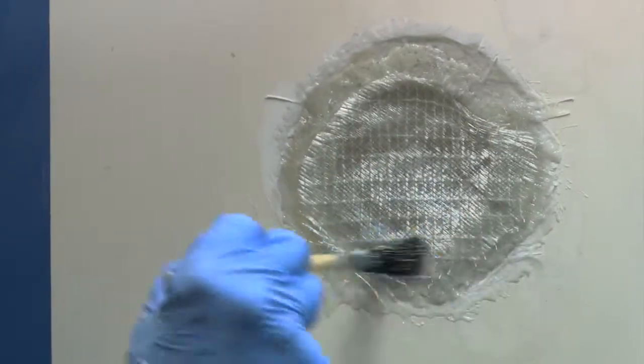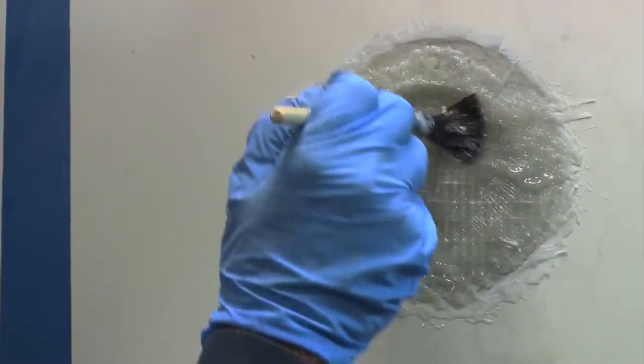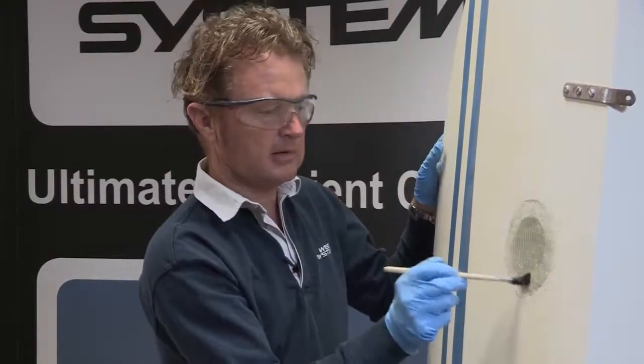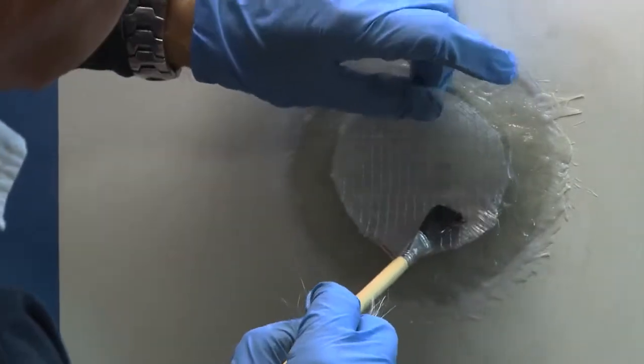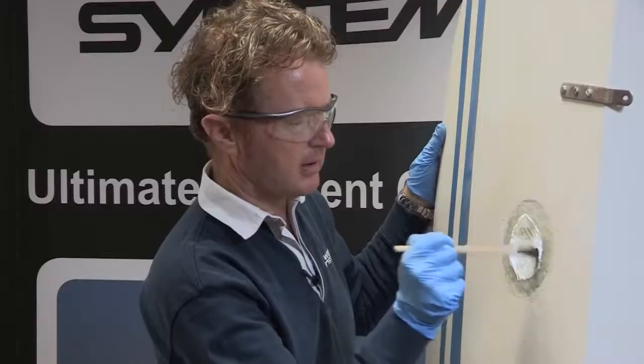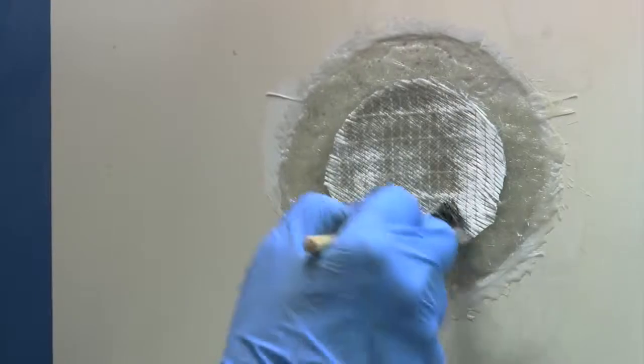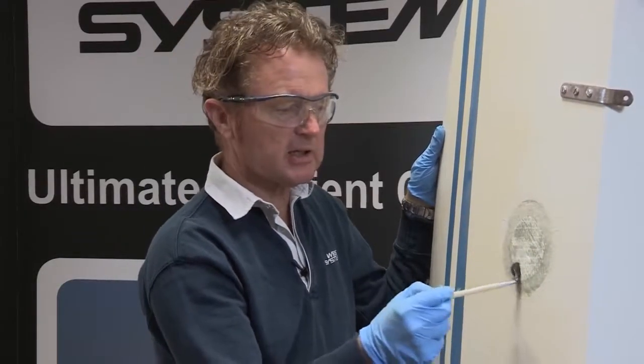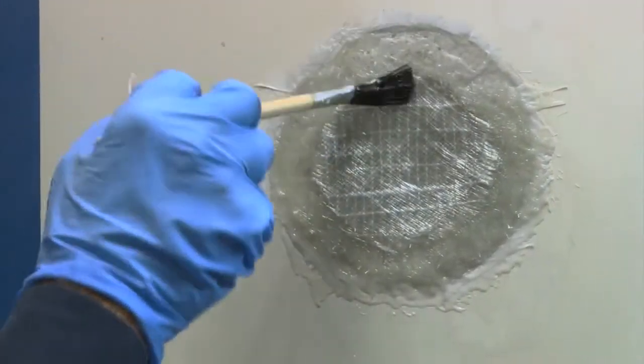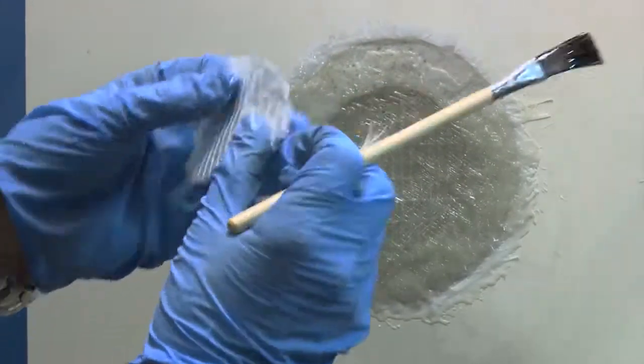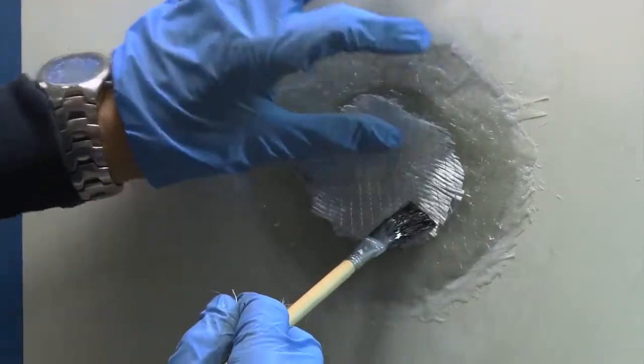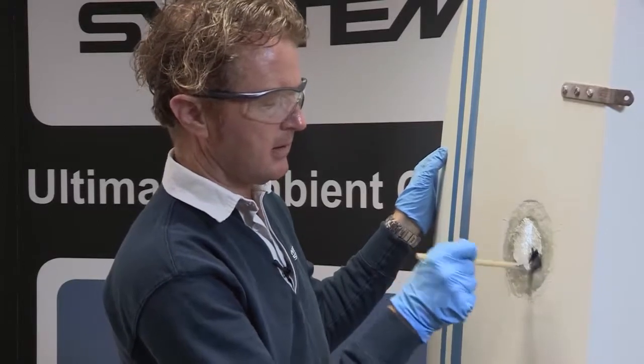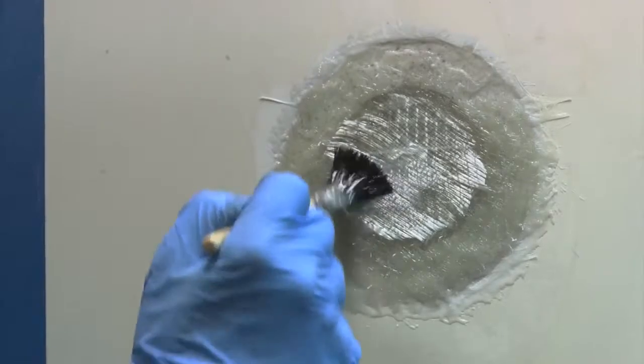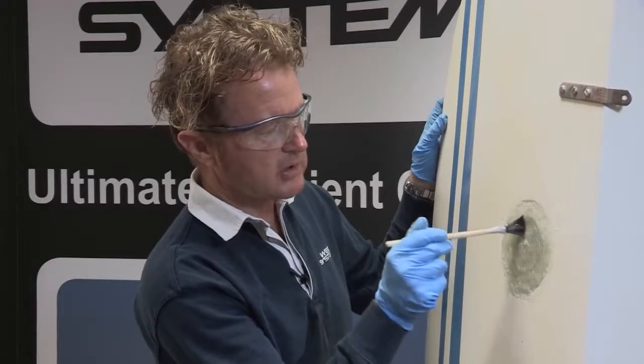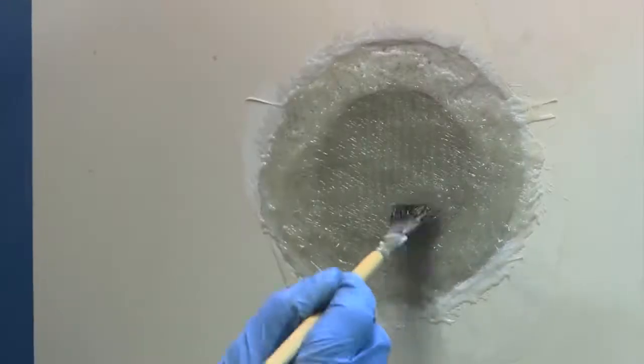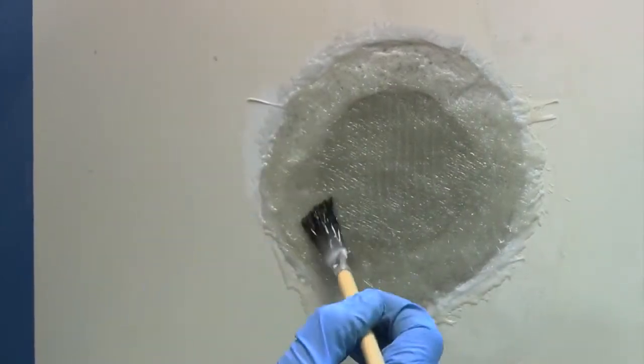A little bit more epoxy. I'm going to use the brush width as a guide to make sure I've stippled everything. Next layer of glass. Make sure that follows the stitching on the last layer. You see how quickly that wets out. This is really not taking very much work at all to effect a really, really strong laminate. Final disc. Make sure it's following the run of the rest of the fibre. Right in the centre of the repair. I'm just going to work on this last patch, make sure I've driven all the air out of it. And that's the major structural part of my repair.